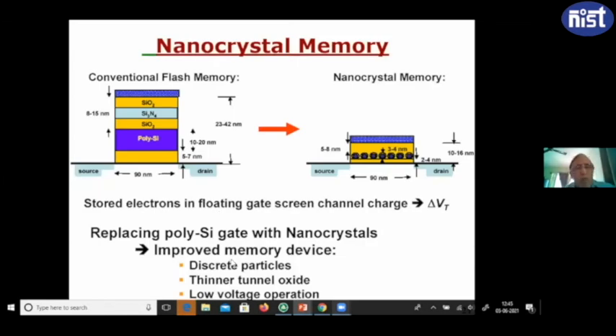The question is, why do we use the nanocrystal? The main reason is that a few years back, most of the conventional memories in the industry were something like this. Instead of nanocrystals, polysilicon was used: the first polysilicon was the floating gate, and the second polysilicon was used as the control gate, and there are some oxides in between. But the thickness of the oxides has to be very, very thin, so there is a lot of leakage. Because of the leakage, it is very difficult to store the charges for a long time. Because this is a continuous net, if there is one leakage, some charges will leak through to the channel and you lose the memory.